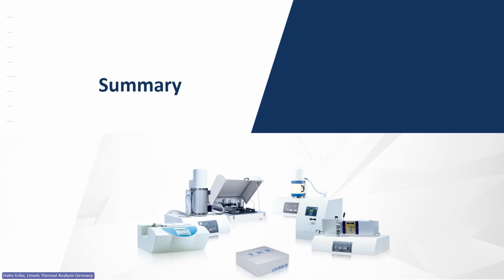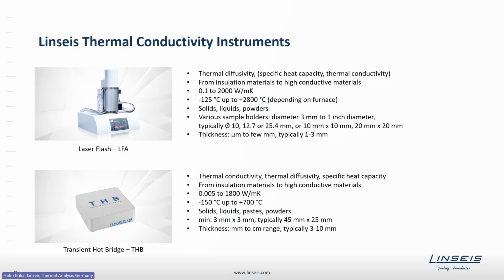Coming now a little bit to the end, we will have a look at a summary of the different instruments. Starting with the transient methods, on the one hand, we have the laser flash analyzer, which is a very universal tool, being able to measure the thermal diffusivity of insulation materials to highly conductive materials, mainly for solids, but with some modifications also useful for liquids, powders, and pastes. For example, the laser flash covers the widest temperature range. Depending on the furnace type, one can go down to minus 125 degrees Celsius, but on the other side, with a special type of furnace, we can reach up to 2800 degrees Celsius.